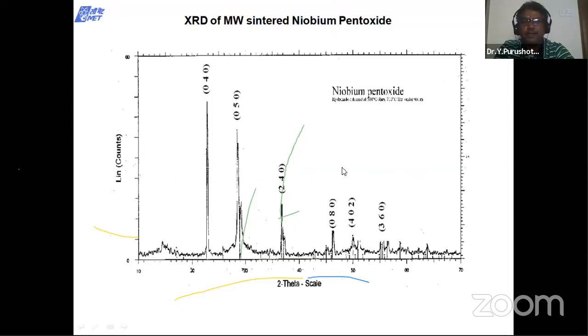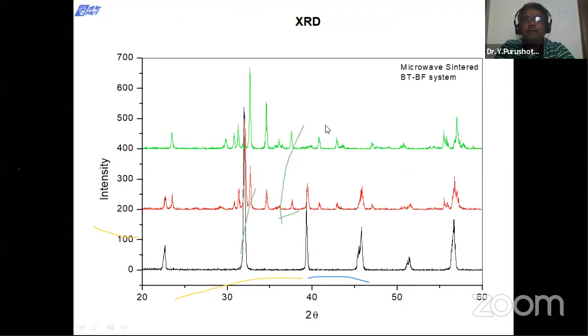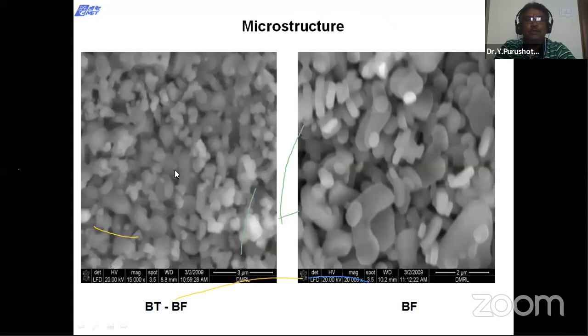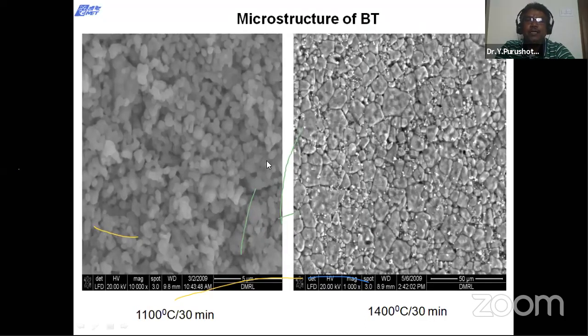This is niobium pentoxide, phase pure, and this is a barium titanate, barium ferrite composite material. So this is the microstructure of the barium titanate, barium ferrite composites, and this is barium ferrite. This is a DMRL sample, and you see high density material. The same barium titanate material we sintered at 1100 degrees centigrade for 30 minutes and 1400 degrees centigrade for 30 minutes. What is the microstructure difference? Enormous grain growth happened. You see, very clear grain boundaries we are able to see, whereas there are not many grain boundaries in the other.